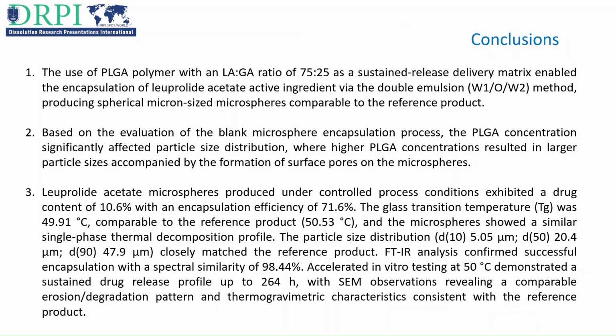As the final conclusions, the main conclusion is that leuprolide acetate microspheres produced under controlled process conditions exhibited a drug content of 10.6% with an encapsulation efficiency of 71.6%. The glass transition temperature was 49.91 degrees Celsius, comparable to the reference product, and the microspheres showed a similar single-phase thermal decomposition profile. The particle size distribution also closely matched the reference product. FTIR analysis confirmed successful encapsulation with a spectral similarity of 98.44%.